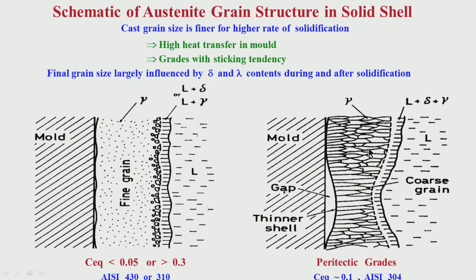Here for peritectic grades which have depression tendency, it is just the reverse. Here the surface, as I have told you, the oscillation mark depth is relatively more in peritectic grades. So, our purpose is to control depression and the depth of oscillation mark. So, here what we have to do? We have to use high frequency of oscillation with low amplitude of mold oscillation. So, the frequency is more here, amplitude is less here, frequency is less there, amplitude is more there. So, the powder is different, oscillation characteristics are different.